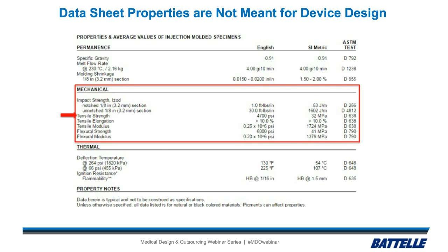They used ASTM D638, and that's a widely used test. It's a great test. The problem is it's always run at 23 degrees C and 50% relative humidity. So if you're going to be using your samples at any other temperature or humidity, you may get a number that's quite a bit different than that. So if you put yours in the refrigerator, then you may get a tensile strength that's significantly different than that because you're 15 degrees C different than where the temperature was for that test.